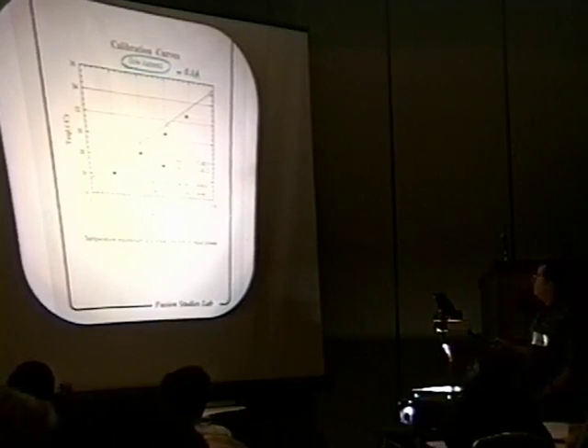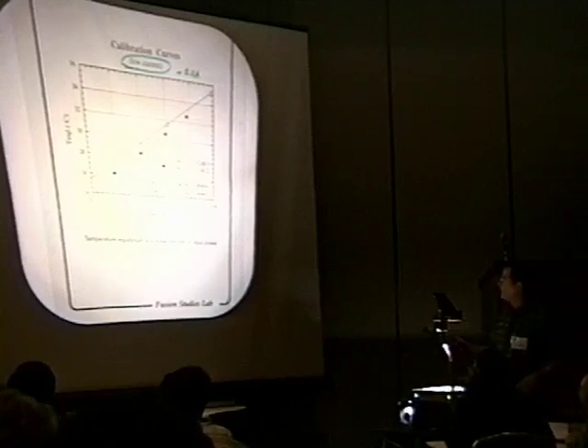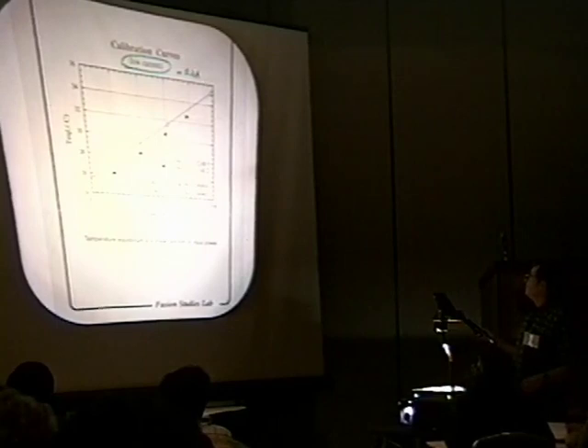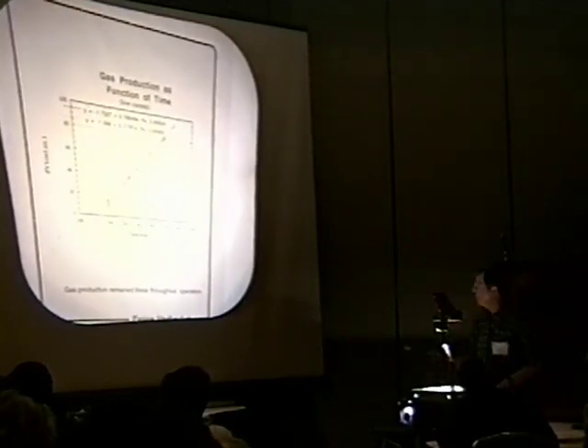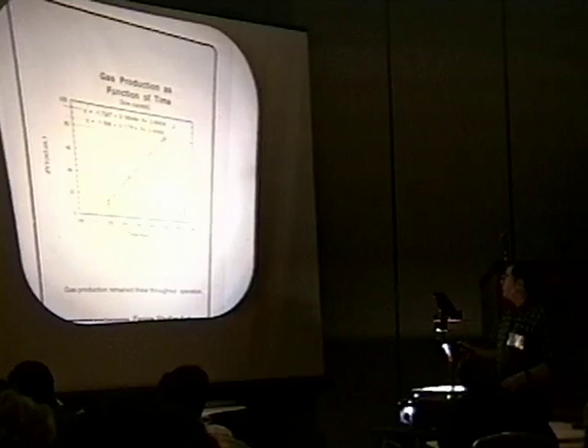For two different cells, we get a fairly nice linear calibration with the 0.2 amp current. The electrodes, as you remember, are 2.5 centimeters square. Gas production is also fairly linear. This is shown for two different power levels as a function of time up to 600 minutes.